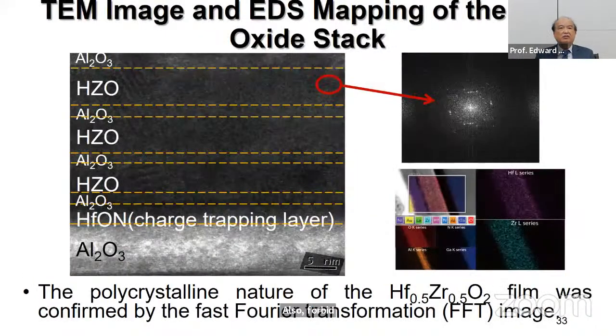And this kind of material needs crystal structures. This hafnium zirconium oxide, when originally deposited, is amorphous, and then it can transform to the orthorhombic phase after 400-degree annealing. So this is the crystalline structure of hafnium zirconium oxide after annealing, and they show that the orthorhombic structure appears after annealing. And it's not so straightforward.